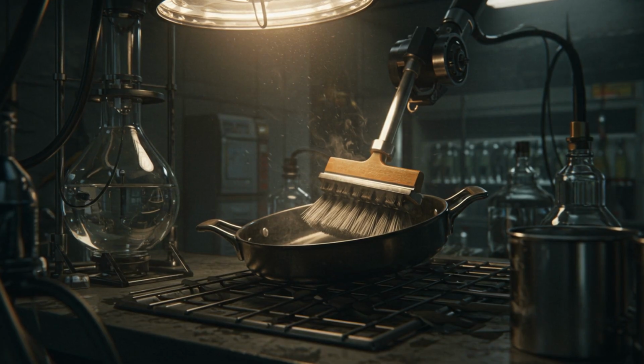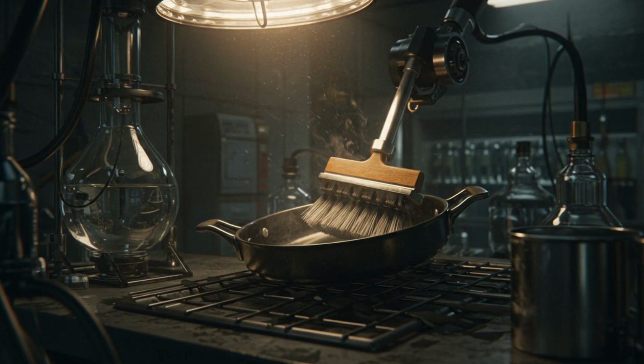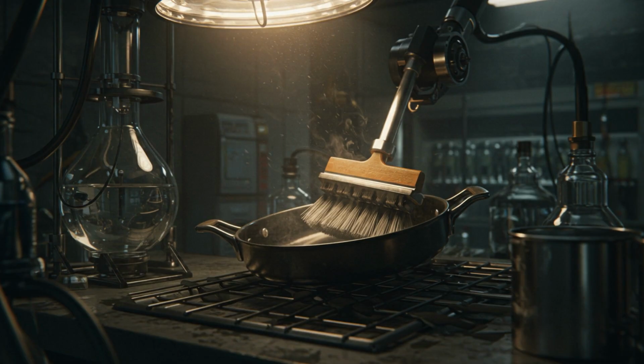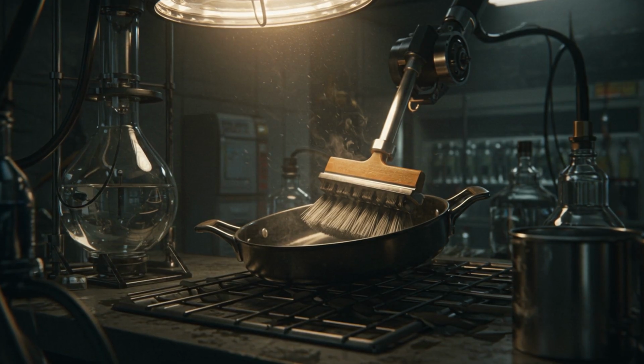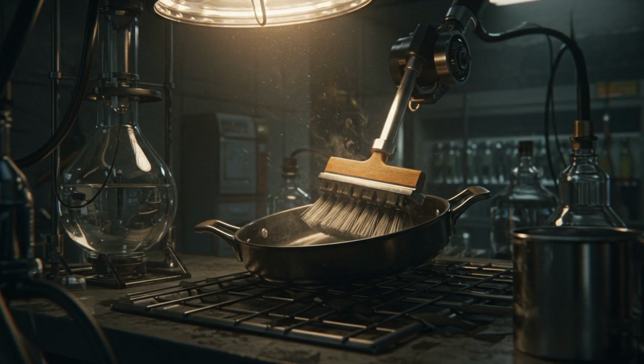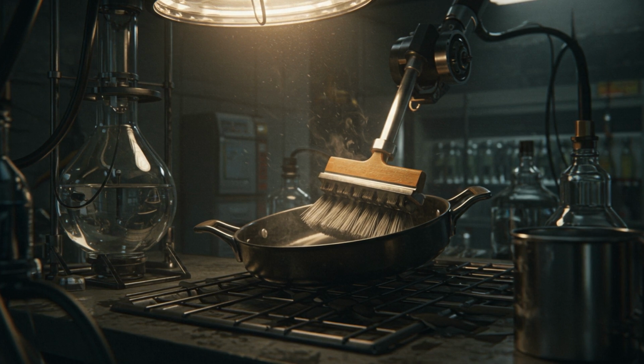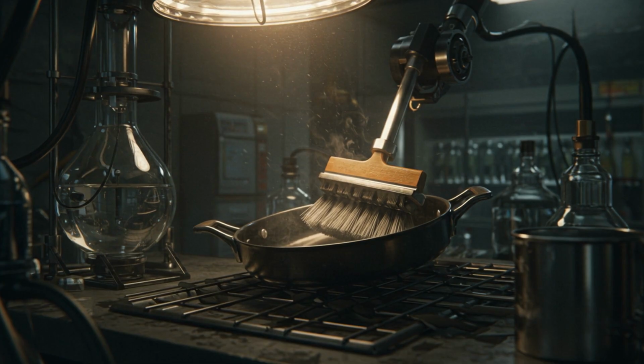Next is the abrasion test. A mechanical arm holding a weighted scrub pad or a metal stylus rubs the surface of the pan thousands of times back and forth. This simulates years of cooking and washing in a matter of hours. Then comes the thermal shock. The pan is heated to maximum temperature and then immediately plunged into ice-cold water. The metal and the coating expand and contract at different rates, and the bond must be strong enough to withstand that violent internal stress without peeling.